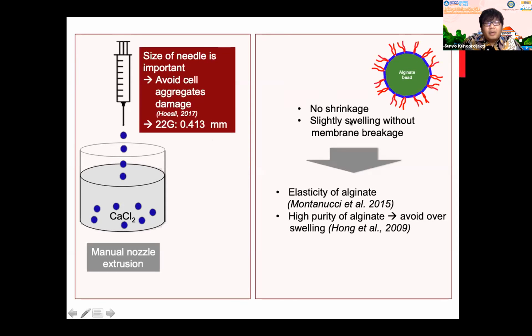Okay, based on our study, no shrinkage was observed, and slight swelling without membrane breakage was observed at the end of the experiment. This phenomenon might happen because of the elasticity of the alginate as well as the high purity of the alginate that we use in this study, which has a beneficial effect in avoiding the swelling.